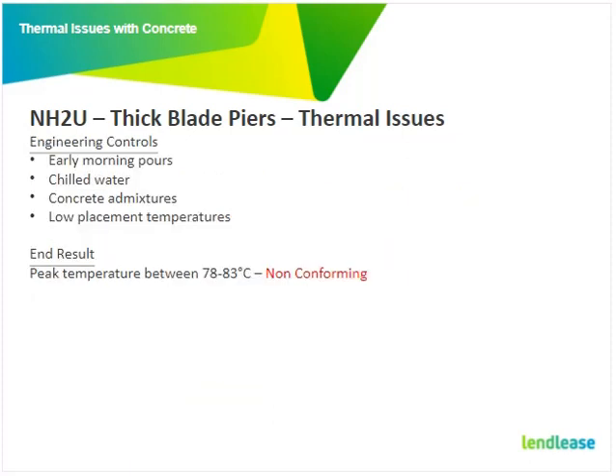What did we do on Nambucca? We had early morning pours, chilled water, concrete admixtures, low placement temperatures, and our end result was 78 to 83 degrees. So some results were non-conforming because the limit at that time was 80 degrees, but if it was 70 degrees, you had no chance. It just wasn't going to work.